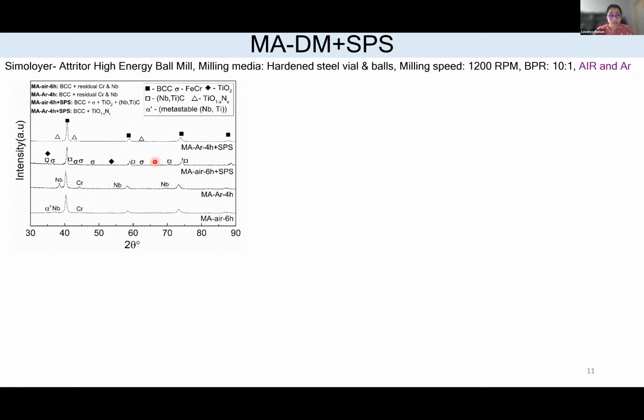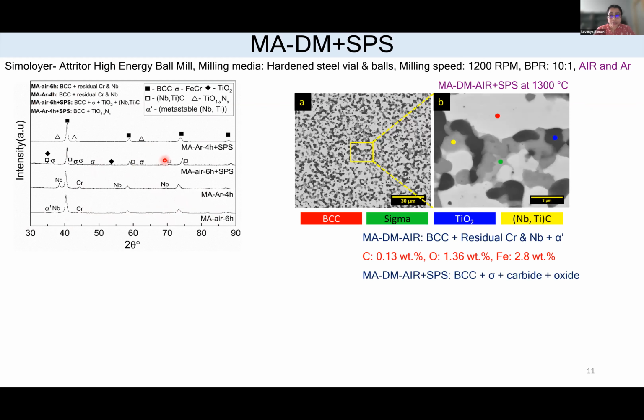But when we sintered these alloys, we have different kinds of secondary phase depending on the milling atmosphere. This is the microstructure of the alloy which was milled in air. When we milled in air, the residual elements chromium and niobium reacted in a different way. As I mentioned, the milling media here is hardened steel vials and balls, so from these we had some amount of iron contamination. The residual chromium reacted with this iron, which has a very strong affinity, and it formed a sigma phase, which is an intermetallic phase. Whereas the niobium combined with titanium, and it formed secondary carbide.